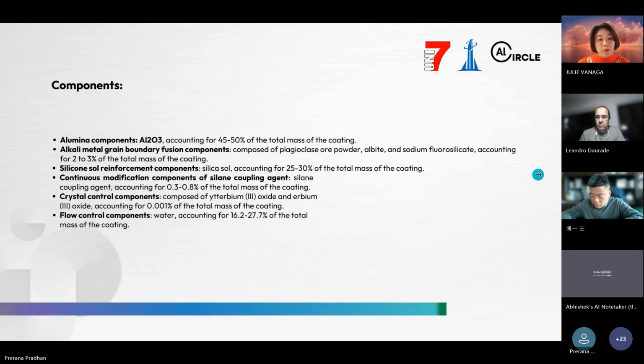You can see 45 to 50% of our composition is alumina. That's the backbone of our coating. It provides high hardness, high temperature resistance, and structural stability, forming the basic framework of the sintered body. And here, I want to emphasize that comprehensive considerations were made in the initial design. On one hand, the alumina can effectively protect the carbon block and achieve energy conservation and consumption reduction. On the other hand, it can safely dissolve together with the molten electrolyte and participate in system circulation.